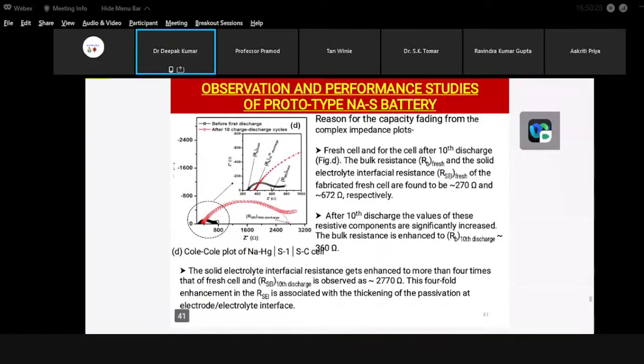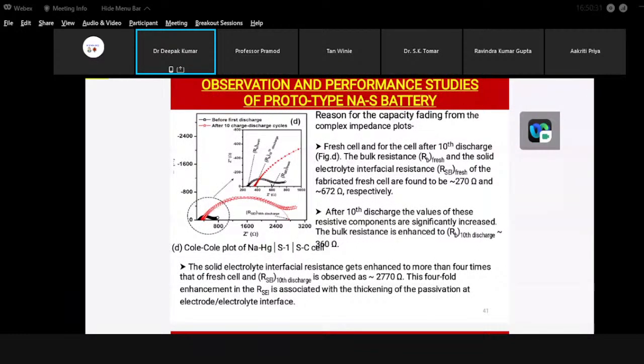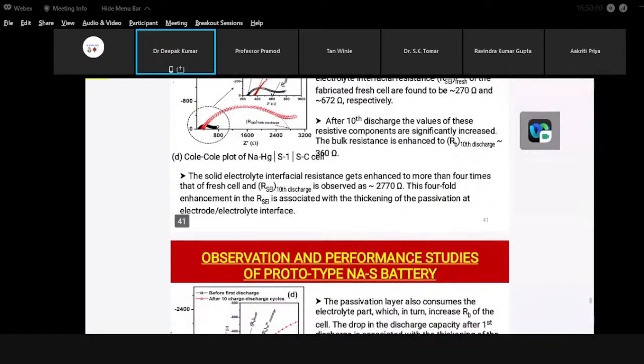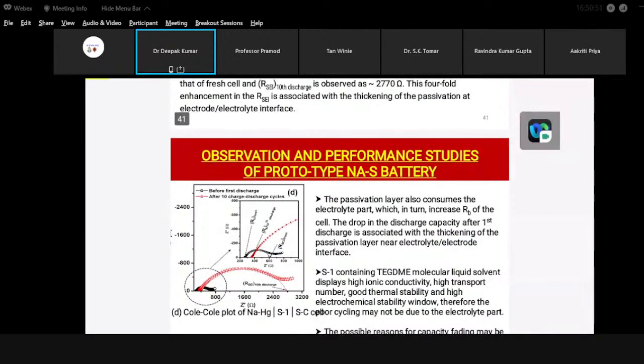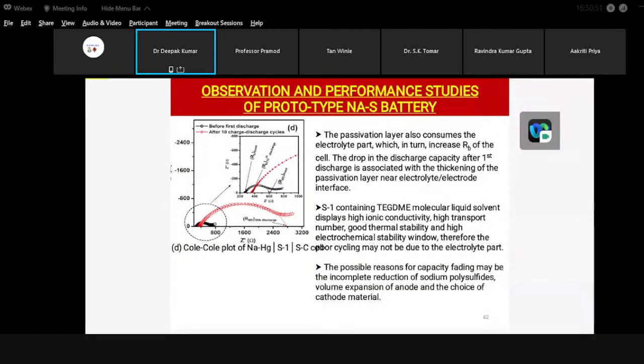I would also like to mention that I have investigated why this is happening, the reasons for this capacity failure. What we observed is that as repeated cycling happens, the interfacial resistance is increasing, which is contributing to this capacity failure. The main reason for this capacity fading could be that we performed these measurements in an ordinary glove box. If we utilize a sophisticated glove box of ppm order, then the results could have been better.